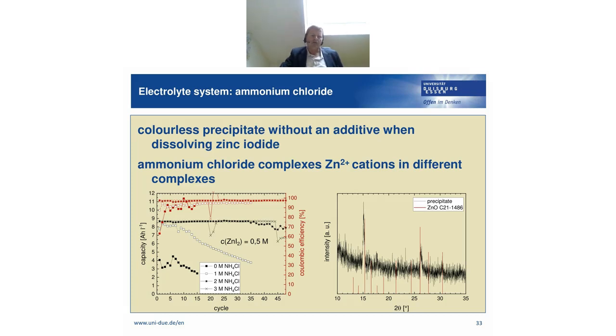We see it here in the graph on the left side. We have on the left axis a capacity in amp-hours per liter, and then we see here the cycles, up to 45 cycles, as a function of the amount of ammonium chloride. And once we add 1 or 2 moles of ammonium chloride, we can obtain 40-45 cycles.